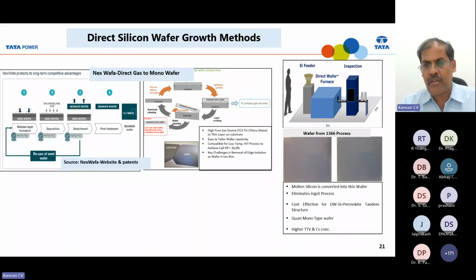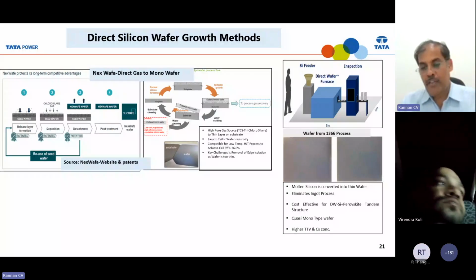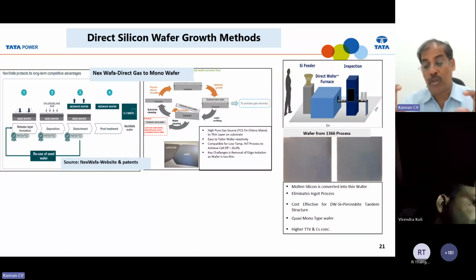And another technique, because instead of polysilicon pouring into a crucible, melting, converting into crystal, there is one technique from the US. One company was trying to establish a new technique called direct wafer. So without any crystal, just pour the polysilicon, then melt it, and just spread it on some substrate, take out the wafer. You can maintain the thickness and all those things. But once again, you can grow whatever shape you want, whatever thickness you want. But unfortunately, you cannot grow very high pure monocrystalline here. You can grow once again in the multicrystalline format.